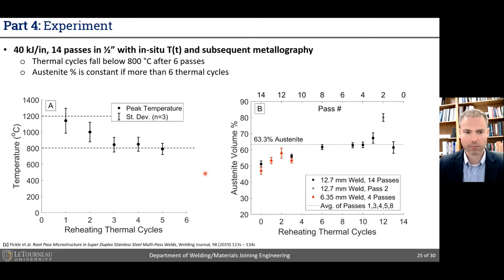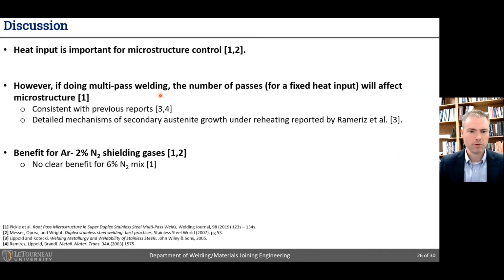And so what we see is that these reheating thermal cycles really do appear to correlate. It's driven by this peak temperature. Total time above this 800 C is critical, well in line with the older literature, such as Ramirez et al. And you can see that the results kind of all fit together. So just to wrap it up today, clearly the key takeaway from all of this is that heat input is really important for microstructure control. However, just thinking solely in terms of heat input, if you're doing multiple passes, we need to think about the impact of these reheating cycles. And this is all consistent with previous reports.